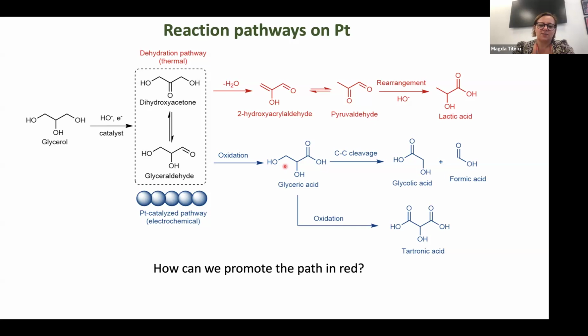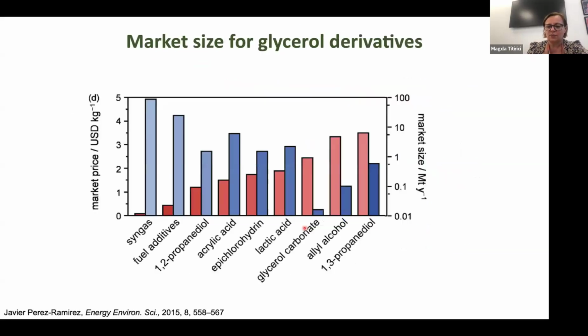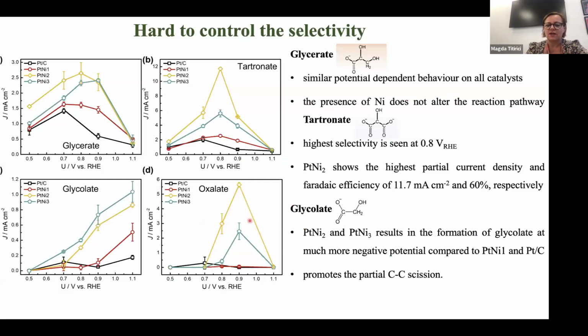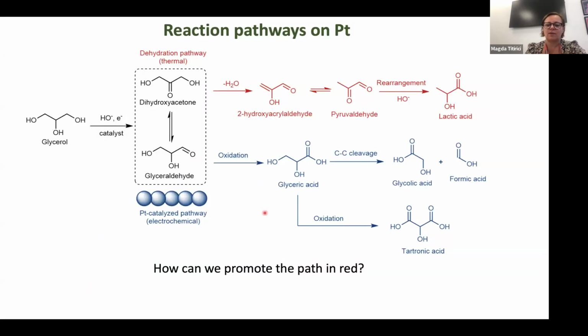And so we did some reading of the literature, where we learned there are actually two pathways. There's a chemical pathway, and there's an electrochemical pathway. Now, on the electrochemical pathway, what happens is you have glycerol. This glycerol forms dihydroxyacetone. This is in equilibrium with glyceraldehyde. And once you form this glyceraldehyde, it oxidizes to form a mixture of tartronic, glycolic, and glyceric acid. So pretty much all of this is what we observe with our platinum, nickel, and platinum catalysts via the electrochemical pathway.